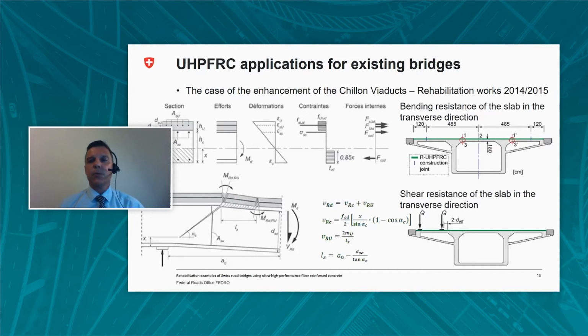There is experimental evidence that in pure bending, no debonding occurs between the concrete section and the new layer, when the concrete substrate has been prepared properly by high-pressure water jet and the substrate has been wetted before the casting. The composite section thus behaves monolithically up to maximum resistance. Based on this observation, the transversal bending resistance of the deck slab is calculated using plane strain analysis. The upper left figure shows the developed forces with ultra-high performance fiber reinforced concrete in tension due to negative bending moment.